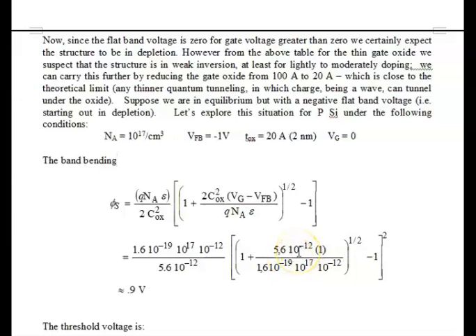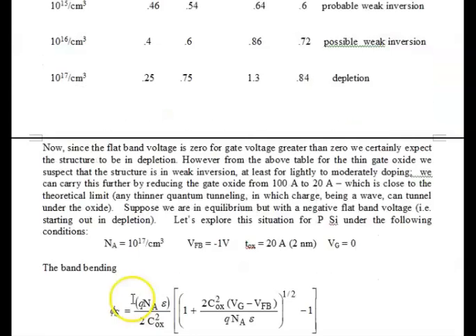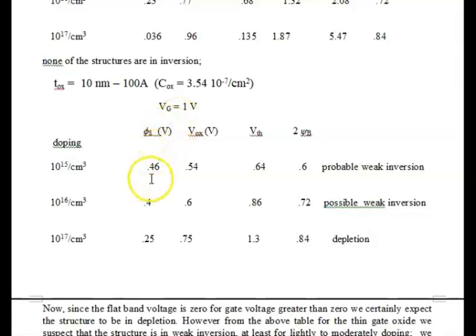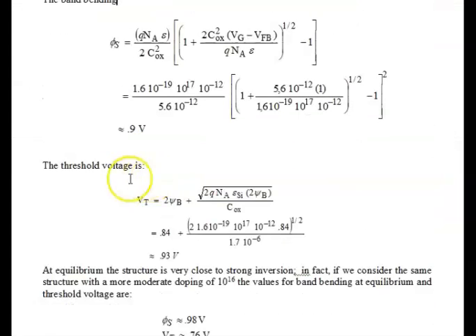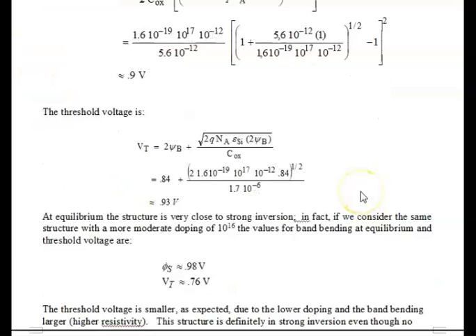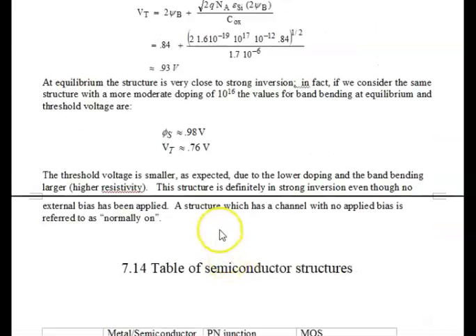Extremely large compared to what we had previously. We get a band bending of 0.9 volts. Really, really a lot of band bending. So even at 1 volt, we didn't have nearly that much band bending. The threshold voltage is 0.93 volts under these conditions, so we would expect this thing to be pretty much in strong inversion. And just one more example, if we go to a moderate doping, we would expect the band bending to go even higher because the resistivity is higher, and it does. It jumps about 10%. The threshold voltage goes down, and if there was any doubt here, there is no doubt here. This guy is in strong inversion even at equilibrium, and that is really a big deal.